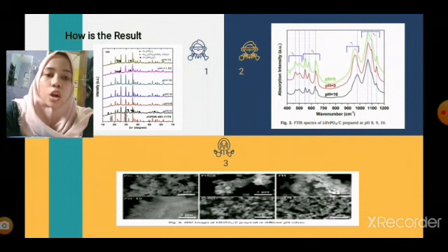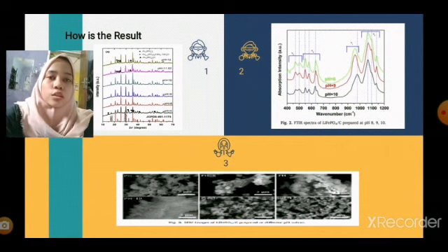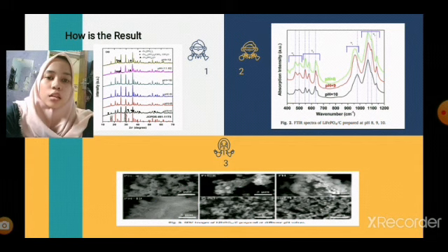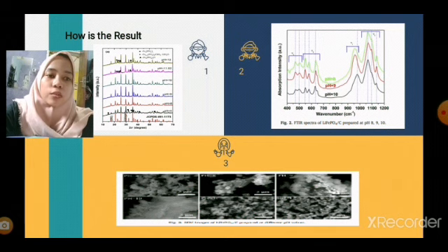diffraction angles. When the pH is 8, 9, and 10, only the pure lithium iron phosphate phase, which can be indexed to the orthorhombic structure with a space group of Pnma, is observed.